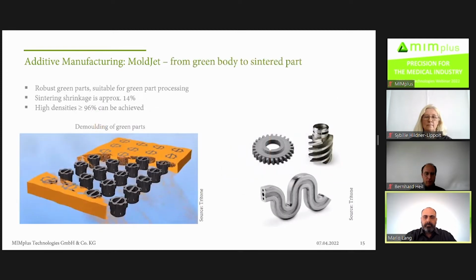After that, of course, you have to remove the mold. So it's melting off and then do the debinding and the sintering of the part. Density is approximately 96%, so comparable to MIM and the other process. And sinter shrinkage is approximately 14%, so nearly the same.